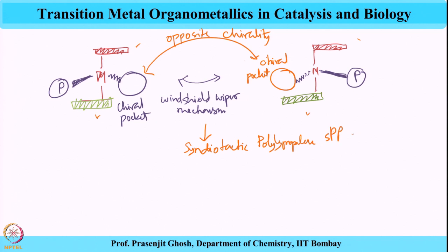Or SPP, which means the methyl groups would be alternatingly incorporated. So, this is a very nice conceptual extension where the principle is that this ligand is chosen with a different symmetry, so that the chiral pockets are of opposite chirality, resulting in the binding of propylene through different faces, and as a result alternating incorporation of the methyl group, one top, other bottom, again top, bottom, would occur, resulting in syndiotactic